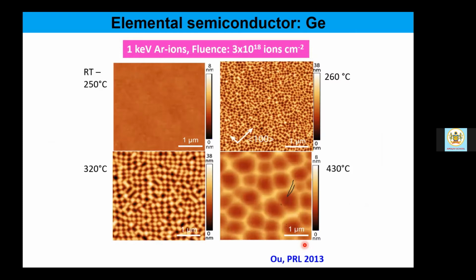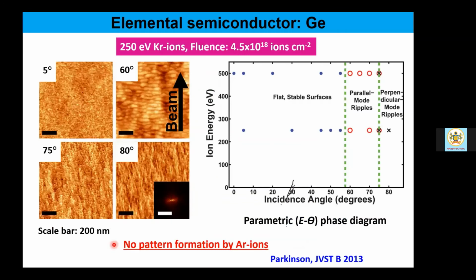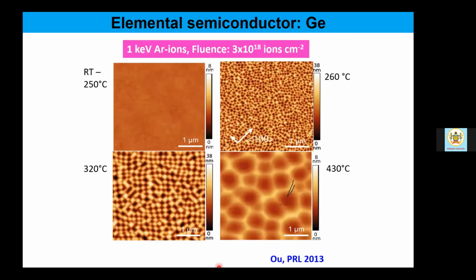The moment we start applying some high temperature to the sample during the same argon ion implantation, which otherwise does not give rise to any pattern formation, as is seen from here and is stated here, no pattern formation by argon ions in germanium, and it remains so up to 250 degrees centigrade. The surface remains flat. What I mean when I say stable surface in the context of ion patterning is that the pattern formation remains absent. So you see, up to 250 degrees centigrade, interestingly, the surface remains flat and stable.